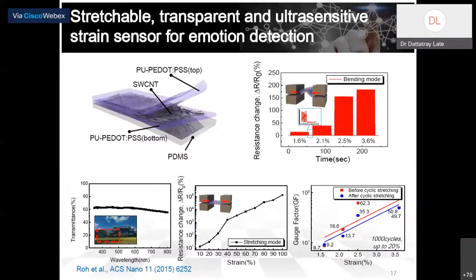For example, this particular device which I showed earlier is based on single wall carbon nanotubes, PEDOT:PSS, and a PDMS mask kept on it. You can see how much is the transmittance of this particular device. You can see the device is almost 60% transmitting. And once you apply strain, you can stretch the device. Okay, you can bend the device. You can see the change in resistance as a function of strain.